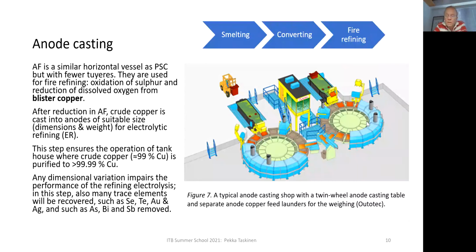And this kind of twin wheel cast shop probably is also in the case of the new Indonesian copper smelter. So this anode copper contains essentially all gold and silver fed into the smelter. It also contains a lot of selenium, tellurium, and those impurities which have not been oxidized away in the matte smelting or in the converting steps.